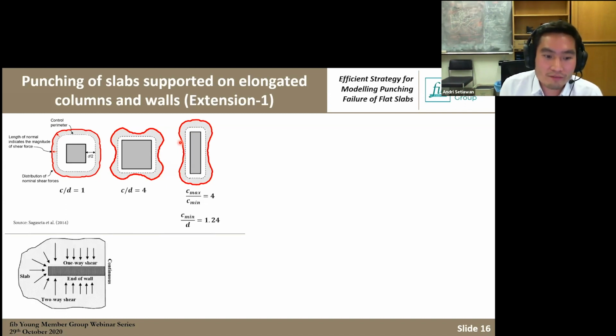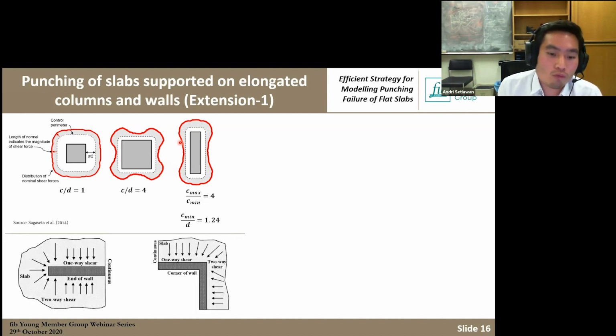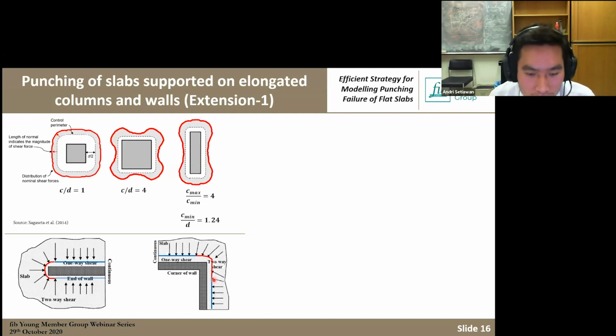This is a very typical situation that we found in practice. For example, if you have a partition wall and also a core wall where you have slabs directly supported by the core wall. So we can see that there is a region with a concentrated two-way shear and also a region with a minimum one-way shear. This happens in both scenarios. You have two-way shear around the corner and one-way shear along the outer part of the region. So what we do in here is distinguish the contribution of the two-way shear in the punching region and the one-way shear in the outer region. But we didn't know at the time what the border is. How can we define a border separating the one-way shear and two-way shear?